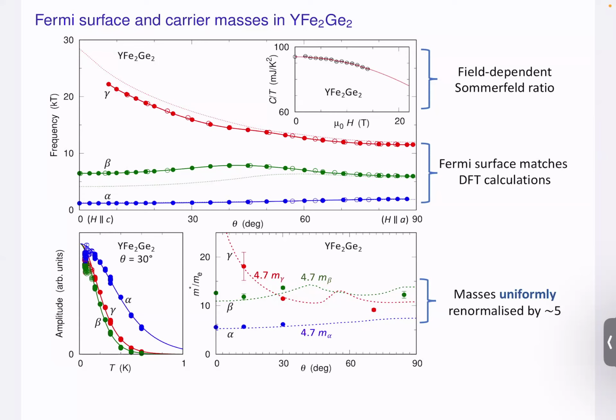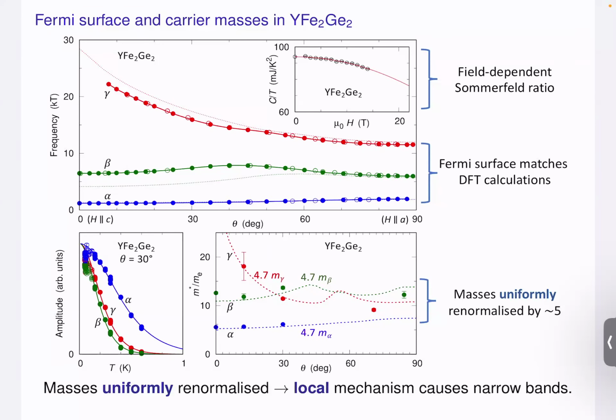At least in first order approximation, that means the mass everywhere on the Fermi surface has been changed by the same factor. It's not a quantum critical phenomenon where you may have hot regions of the Fermi surface connected by critical wave vectors associated with fluctuations, and you get a mass renormalization there, and they stay unrenormalized elsewhere. It's the same everywhere. So this measurement suggests that there's a local mechanism driving the mass renormalization. There'll be more, of course, because it's close to the border of magnetism, and there's superconductivity. There'll be more phenomena, but the baseline mass renormalization is presumably local because it happens similarly in all directions on all parts of the Fermi surface.